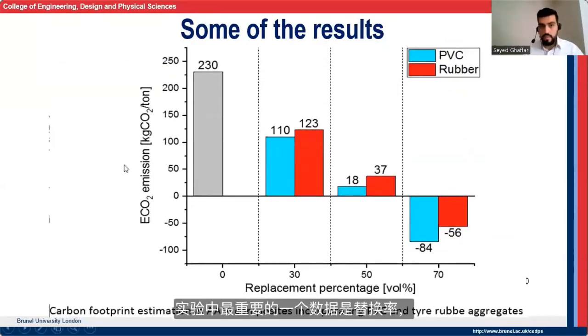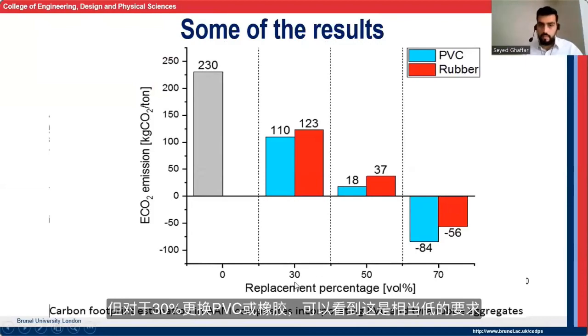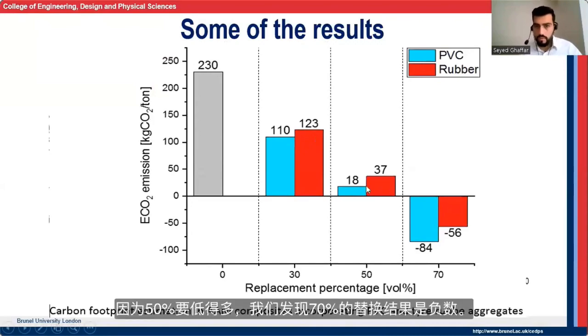One of the most important figures here is actually the replacement percentages and the equivalent CO2 emission. For the control sample it is 230 kilograms CO2 per ton of the material. But for 30% replacement with PVC or rubber, you can see that it is considerably lower. For 50% it is a lot lower. And we found that for 70% replacement it is actually negative.